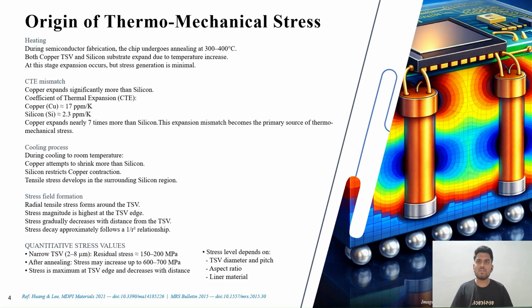So when the structure cools down to room temperature, copper tries to shrink more than silicon. However, the surrounding silicon restricts its contraction. As a result, tensile radial stress develops in the silicon around the TSV. The stress is maximum at the TSV edge and gradually decreases with distance, approximately following a 1 over r squared decay behavior. Typical residual stress values for narrow TSVs can range from 150 to 200 megapascals, and after annealing, stress can increase up to 600 to 700 megapascals. The stress magnitude depends on TSV diameter, pitch, aspect ratio, and liner materials. This thermomechanical stress directly affects nearby transistors, which is why stress modeling is critical for reliable 3D IC design.